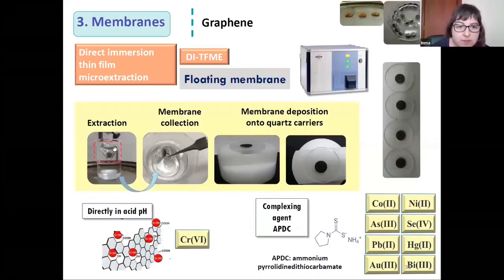Here we can see how this membrane acquires a conical form during agitation in vortex form in the sample solution. And here we can see how with these tweezers and the glass substrates we can manipulate or handle this membrane. We use these graphene membranes in direct immersion thin film microextraction for the extraction of chromium-6 at very acid pH. Another application we have is by using complexing agents such as ammonium pyrrolidine dithiocarbamate, which is a typical metal chelate, and we form a chelate with all of these elements, and we are able to preconcentrate them into the graphene membrane: cobalt, arsenic, lead, gold, nickel, selenium, mercury, and also bismuth.